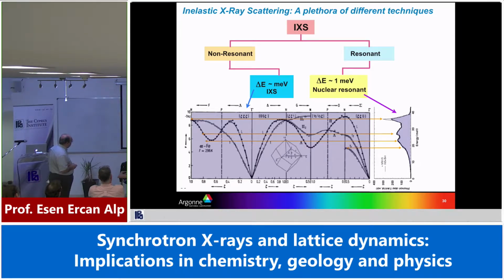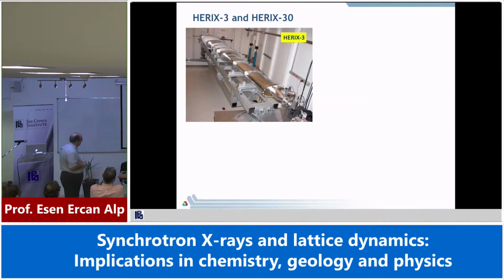So this is something called phonon dispersion curves. Has anyone studied solid state physics? Obviously you have, right? And you have seen these graphs before, right? So if you have a single crystal, you can actually measure phonon dispersions point by point. If you use the nuclear resonance scattering, you can actually measure this entire thing using phonon density of states. And once you have phonon density of states, most of the additive properties of thermodynamics come into play.